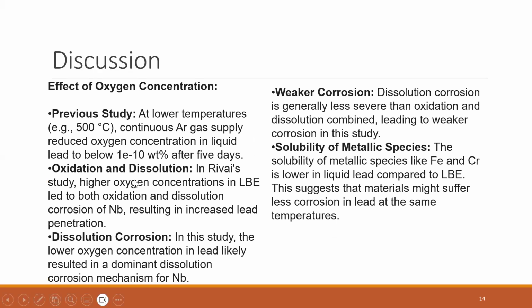And talk about the effect of oxygen concentration in previous studies at lower temperatures. At lower temperatures, 500 degrees Celsius, continuous argon gas supply reduced oxygen concentration in liquid lead to below 1 times 10 to the power of minus 10 wt% after 5 days.